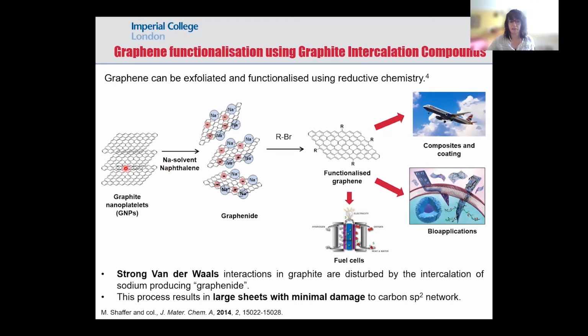To exfoliate graphite, the sodium intercalates between the layers, and the negative charges repel these layers, so they separate electrostatically. And we can use these negative charges to react with a specific molecule. This way we can customize the final graphene. We can add specific functional groups if we want to prepare graphenes compatible with composites, in bio applications or